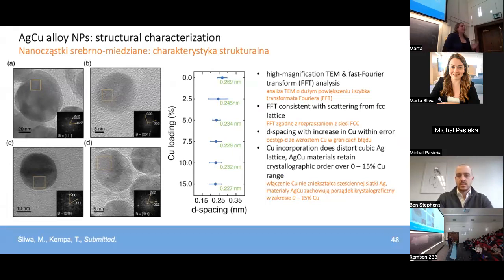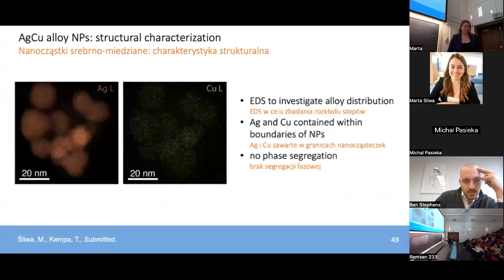So we saw through fast Fourier transform derived diffractograms and TEM analyses of these samples that the spots that we see in these FFT diffractograms are consistent with an FCC lattice for silver. And we also see negligible change in the d-spacing of these products. There are some differences, but they're within the statistical error of our analyses. And all of this data collectively indicates to us that even as we increase the amount of copper, the underlying cubic silver lattice is retained and there's no major structural effect.